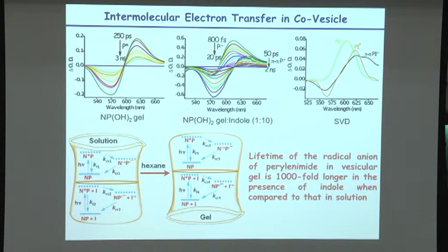So what we proposed in this particular work is that if you are making a photovoltaic device, all you need to do is not mix donor and acceptor just like that, but instead organize one of these, either donor or the acceptor, and throw in the other material. It is going to give you a long-lived charge separated state with the same components that you are mixing together.